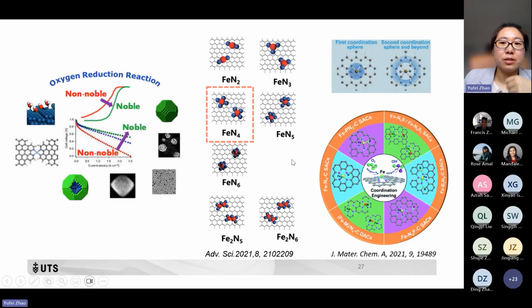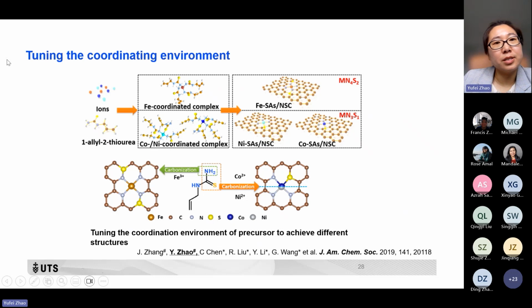So for my research work, the first one, we would like to tune the coordination environment of the iron-based catalyst. The method we used is to utilize the same carbon precursor while changing the metal ions, like iron, cobalt, and nickel. We found it can achieve quite different atomic structures. We assume that the interactions or affinity between these ions and the ligands in the carbon precursors lead to the different atomic structures.